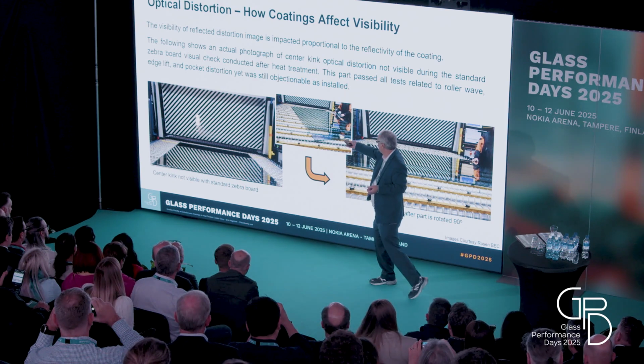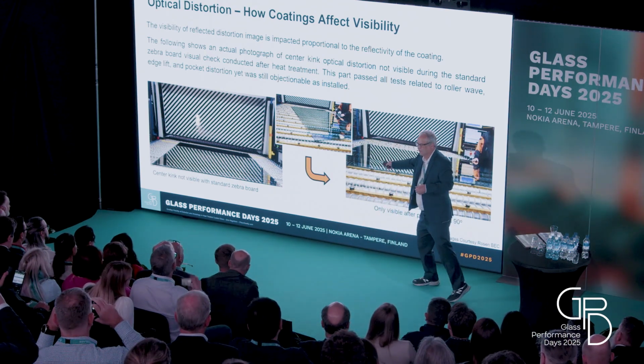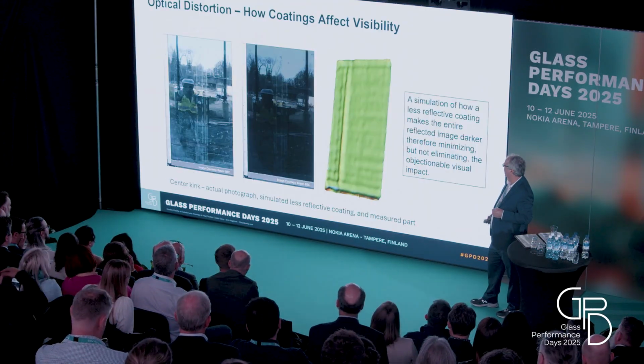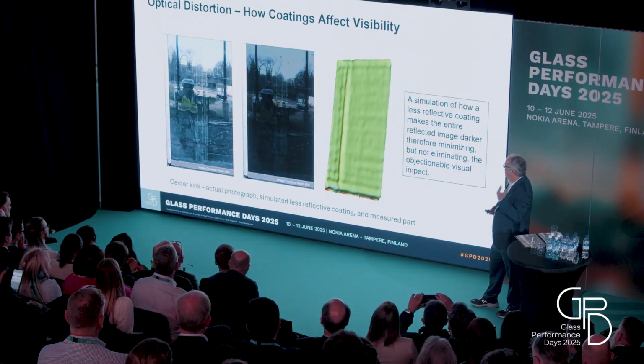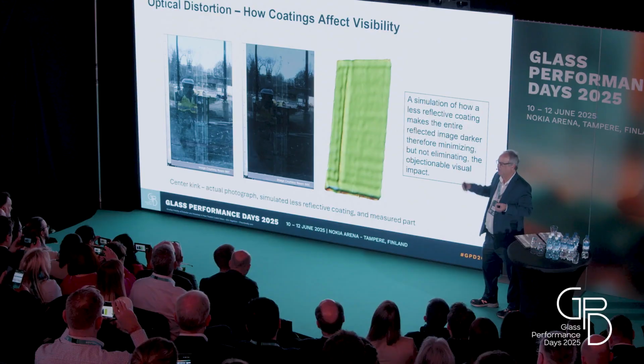But the interesting part is, as you rotated it around 90 degrees, that is the only time you were able to see this fine distortion in the direction of travel. And this is what I wanted to point out, and this was exacerbated by the coating.